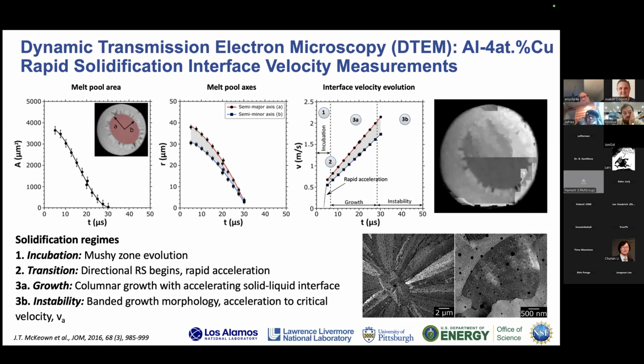And basically the way that it works is you sputter deposit a 100 nanometer thick film on an amorphous silicon nitride substrate. You can then hit this with a laser and you can create a molten metal pool, and then you can watch solidification dynamics at very high spatial and temporal resolutions, much higher than you could do, for example, with synchrotron X-rays.